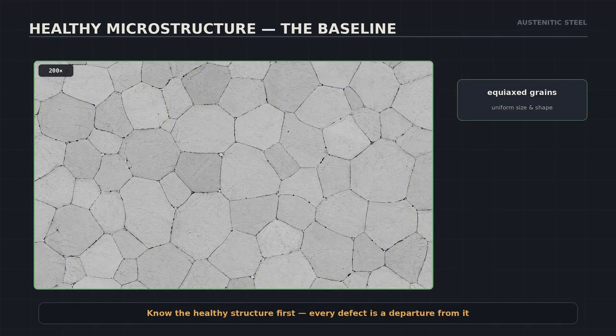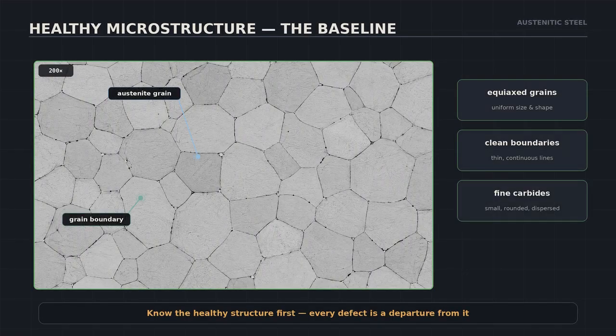Before hunting defects, know the baseline. This is healthy austenitic steel. Equiaxed grains, all roughly the same size. Clean, thin grain boundaries. And fine carbides, small, rounded, evenly dispersed. Notice what's not here, no voids on the boundaries, no continuous films, no cracks. Every defect in this video is a departure from this picture, so fix it in your memory.